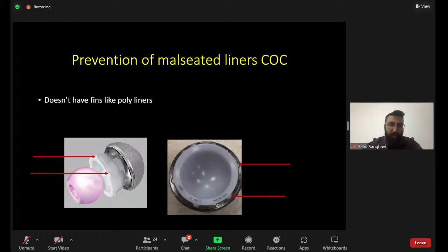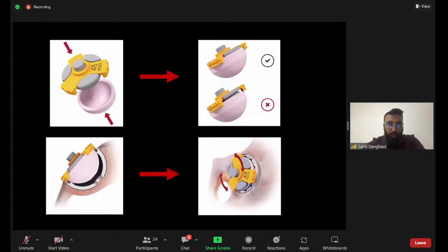Remember, one disadvantage in a ceramic liner is it does not have these pegs or fins, which you can see in polyethylene liners, which allow you easier locking with the shell. So that is why mal-seating liners is a problem with ceramic. So you have this, this is the one which is provided by the DePuy company, and you have this liner inserting surface or liner inserter, which is basically like a fin. So your ceramic liner can get attached into the fin. You simply plug that around the rim of the acetabular shell and you rotate it once to make sure there is no interpositioning soft tissue.